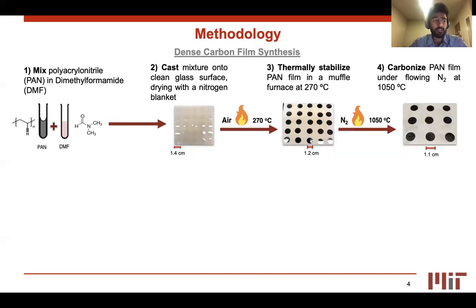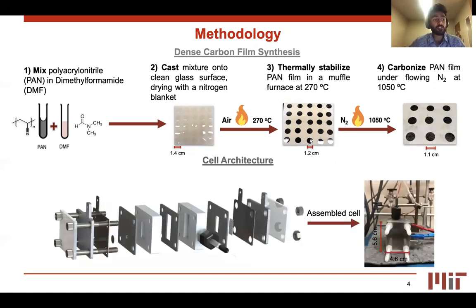Finally, the thermally stabilized discs are carbonized under nitrogen at a temperature of 1050 degrees C to form the non-porous and planar carbon films, where the average retention was 66% with a standard deviation of 5%. An in-lab customized cell architecture was used with the synthesized electrodes, whose schematic is as shown below.